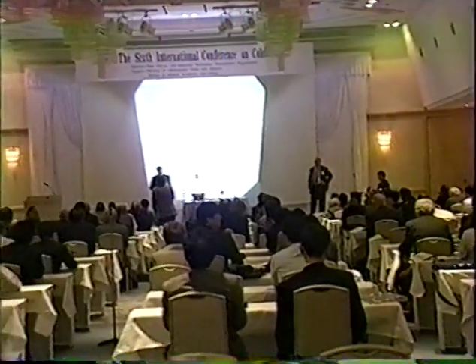Please, can you tell me what the current density is during the excess heat period? Well, for the ones I've shown here, the charging is always done at about 20 to 100 milliamps per square centimeter, and we increase the current by a factor of 5, so it would be 5 times 20 or 5 times 100, so up to 500 milliamps per square centimeter.